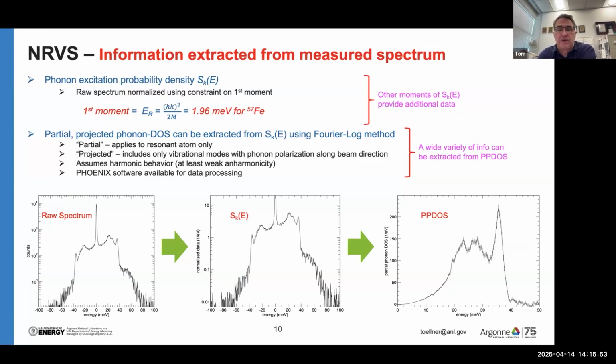From that, you can apply a procedure, a Fourier-log deconvolution method, that allows you to extract the partial projected phonon density of states. This is done with software that we have available. This is Phoenix software, and I will show you where you can get that software and more later.